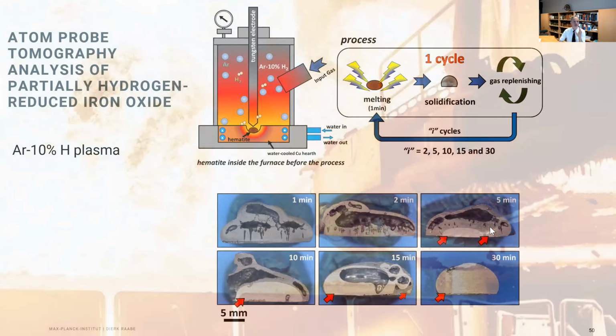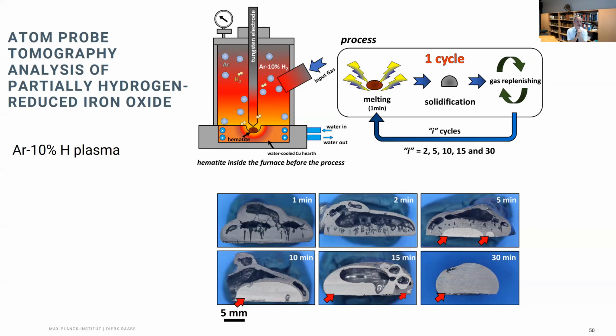Now, we mimic this process in our laboratory. Of course, not in this big size, but as this technique in principle exists in large quantities, we modify it. That is one project in our institute where we work with a couple of colleagues together. What we do here, however, is we don't use the furnace in the same setup, but we expose it to a mixture of argon, just an inert gas, which is not doing too much except enabling some recombination in the plasma, and 10% hydrogen. And we create a plasma from this through the electrical energy that comes through these electrodes.